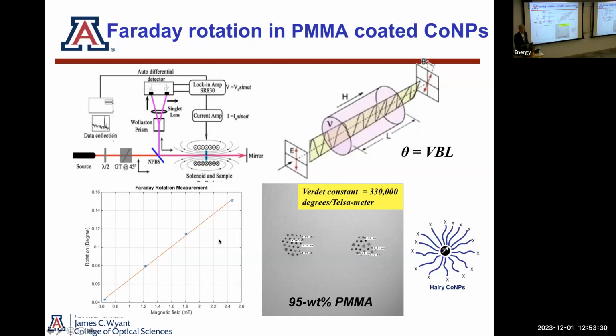So when you make these composites well, you can get very high Verdet constants. This is actually a measurement of the rotation. Now, these are pretty thin samples, so we're talking about fractions of a degree rotations that we measured for these samples that we put in this system.